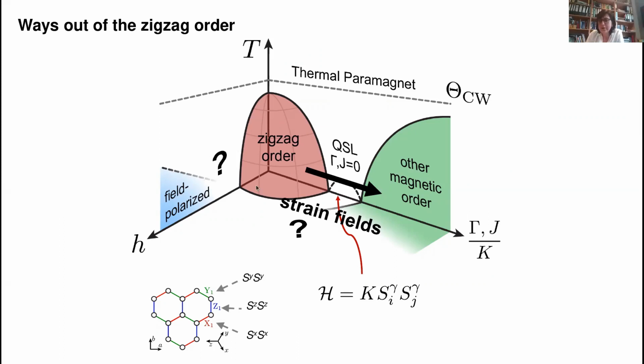But there is another way of bringing the system out of this zigzag order, which is by straining the system, because these materials have a very strong coupling to the lattice - a strong magnetoelastic coupling. So you would expect, if you are able to manipulate the system with strain fields, you will be modifying these coupling constants and bring the system maybe more to this Kitaev limit.